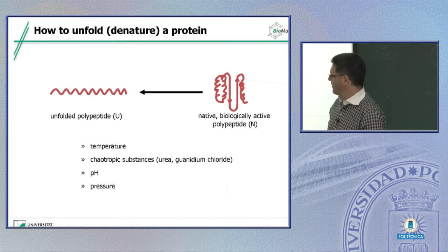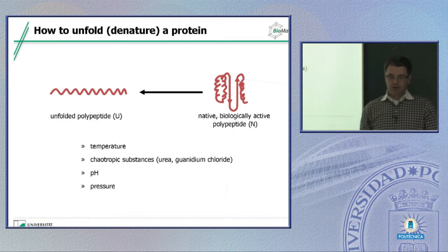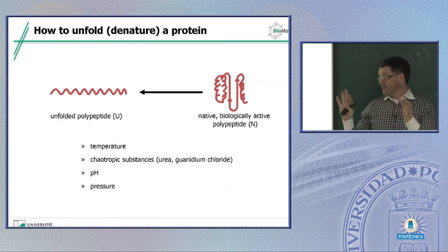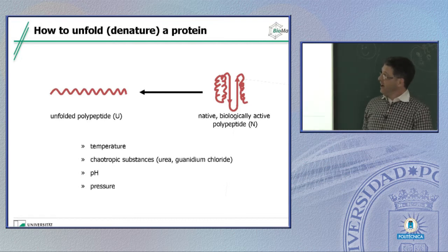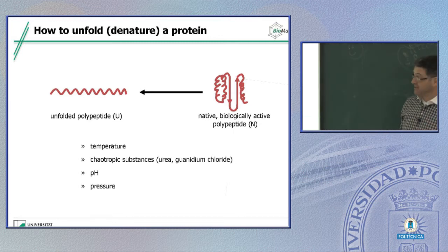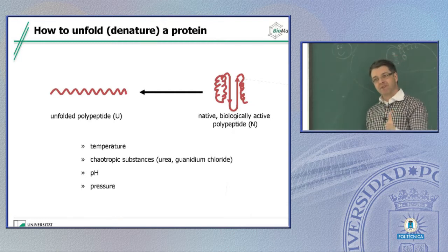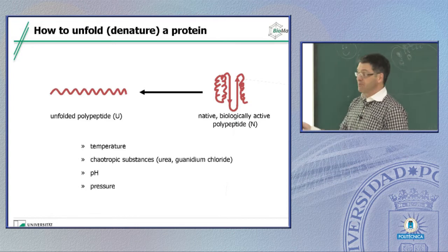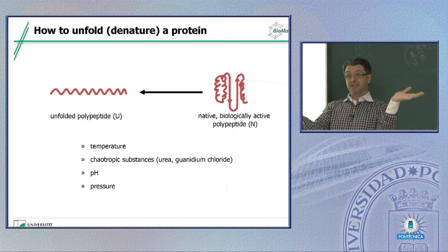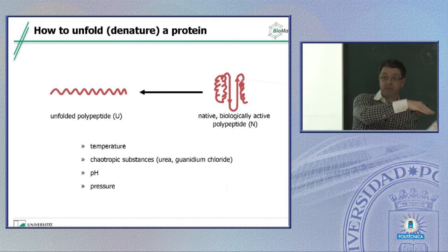You can work with supercooled solutions, but you have to add a lot of salts. But theoretically, it's no problem to cold denature proteins. Practically, it's complicated. But it would be the smoothest way because just by raising the temperature, you can refold it, which is not the case with high temperature, because if it's aggregated and you lower the temperature, you cannot come back.